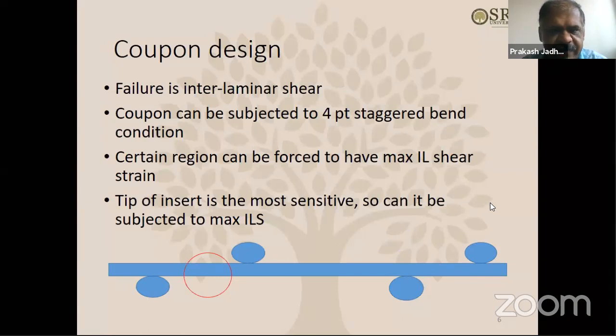So going ahead, the approximate size of these coupons was about 30 centimeters long. A representative layup was used, similar to the blade layup. But this is a constant thickness, not like the blade which has a very variable thickness, just to have a representative coupon in a standard UTM setting. You go to the universal test machine, you have the 4-point bend setup and you do the staggered 4-point bend. The width was 1 inch and the thickness depended upon the number of layers.